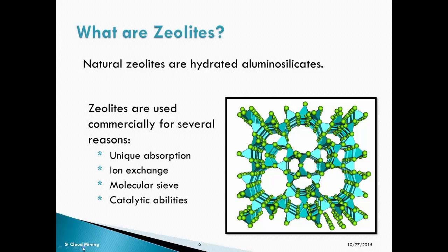They have the ability to act as a molecular sieve, and that just means that on an angstrom level, they can separate one type, usually of an organic compound, from another. In the case of zeolites, usually it's a straight chain hydrocarbon from a branch chain. The straight chain can go through the channels of the zeolite. The branch, an arm sticks out, gets caught, and a separation of different molecules is made at that point.